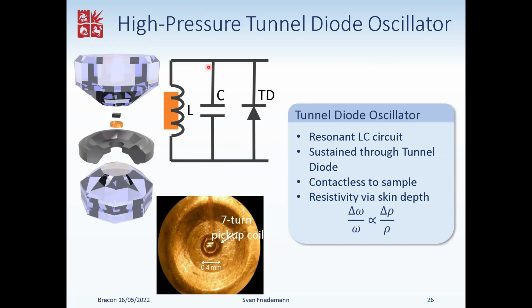And then this coil is part of an LC circuit, which is driven by a tunnel diode and hence maintains its oscillation. Now, the resonance frequency of this oscillator will depend on the inductance of the coil, which itself depends on the skin depth of the sample, because essentially the volume that's available for the coil to create a B field is limited by how far you can go into the sample. So that's how you get a link to the skin depth. And the skin depth itself is, of course, related to the resistivity of the sample. So it's a contactless probe of the resistivity.